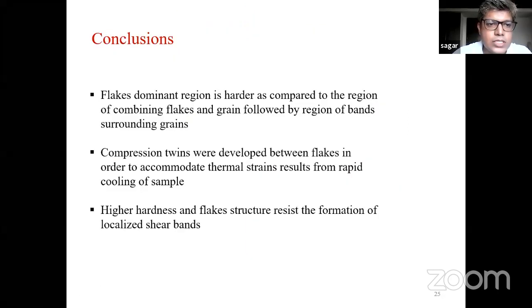So these are the conclusions from this. The flakes dominant region is harder as compared to the combined flakes region, followed by the grain boundaries on the bands. Then we have seen that the twins formed were compression twins. And higher hardness and flakes structure resisted the formation of localized shear band. So the third conclusion is the main conclusion of this study.